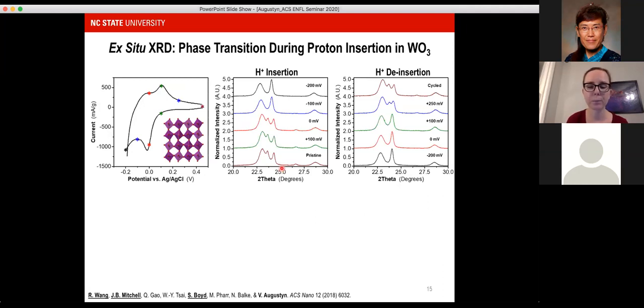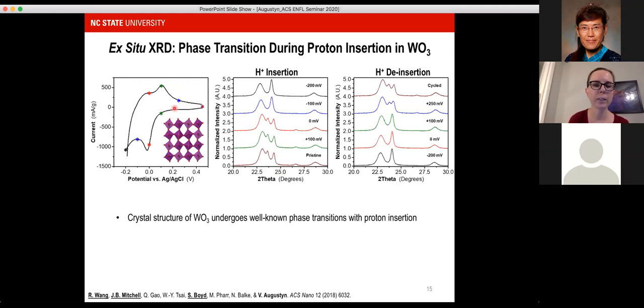Our initial hypothesis was that, of course, the protons must be moving through the hydrated interlayer. So we did ex situ X-ray diffraction of the proton insertion in the anhydrous tungsten oxide, and this shows what's well known in the literature, that the material undergoes phase transitions with proton insertion. So here we have a cyclic voltammogram. We're taking an X-ray diffraction pattern at these different points during the proton insertion and then the proton deinsertion.